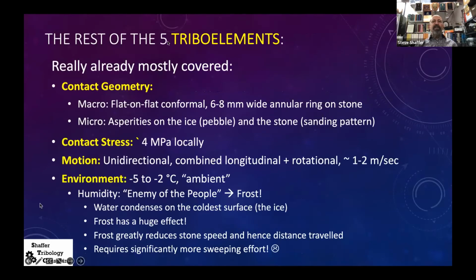So let's cover now the rest of the 5 triboelements. That was all materials. The contact geometry, we mostly covered that. The macro geometry is flat on flat, conformal is what I call it. And that's the 6 to 8 millimeter wide annular ring on the stone. And the micro are these asperities, or the pebble on the stone. We saw images of that. And that's due to the sanding pattern on the stone and the asperities on the ice. The contact stress we saw was about 4 megapascals locally.